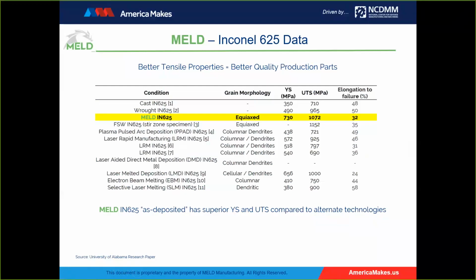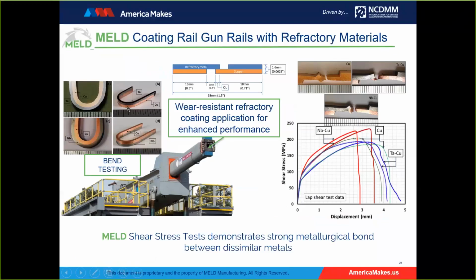Another coating application, a gun rail joining copper to refractory metals. Again, we passed the bend test and so forth, but I want to point out here in the slide the shear stress results. There's copper on copper, copper on tantalum, and copper on niobium. The shear stress test specimens show the fracture occurred away from where we joined the dissimilar metals. You'd think where we joined dissimilar metals, the copper to the 2 refractory materials, that may be our weakest point of the test specimen. As you can see, it fractured away.